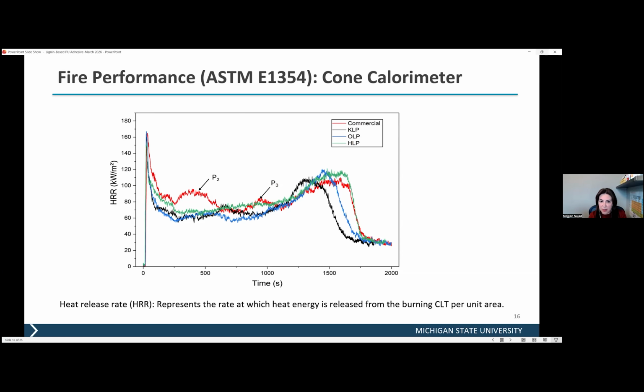Now, this is a 3-ply CLT, small CLT samples. The first glue line, bond line, and the second one. This is an indication that with the polyurethane commercial adhesives, we see some burning of the adhesives and generating heat, and that comes from the adhesives in the second line too. But the lignin-based adhesives, because of the aromatic structure of lignin, create char and prevent this burning of adhesives and generating heat.